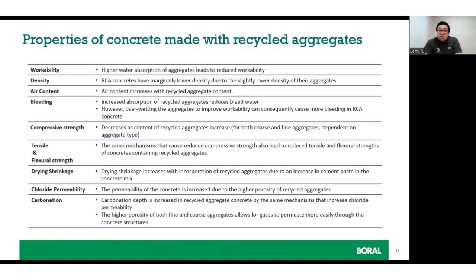Since the surface of the recycled aggregate is attached to a large amount of aged cement slurry, this will increase the number of pores and cracks, resulting in lower workability and lower mechanical properties of the recycled concrete compared with natural concrete. So, for example, the higher water absorption of aggregates leads to reduced workability of concrete, thus making concrete difficult to pump. Compressive strength decreases as the content of recycled aggregates increases. This is for both coarse and fine aggregates.